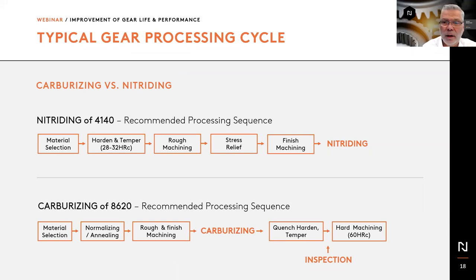and quality and distortion, is the process temperature and the sequence of processing. At first, of course, there is a material selection, and the material that has been selected for an application, depending on torque, on loading, etc., and speed, will be hardened and tempered. You'll see here it's commonly 28 to 32 Rockwell C, but the quench and temper can also be done to a higher